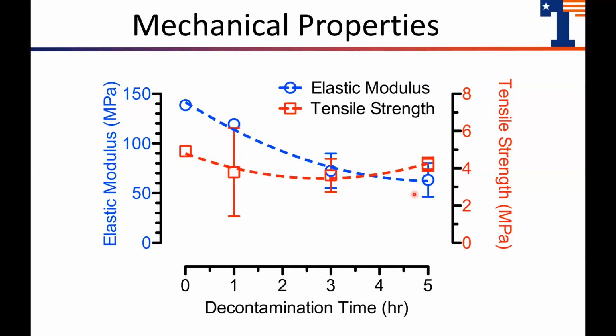Since the elastic modulus decreases, it suggests there's an increase in the plasticizing effect. Then you also have a decrease in the tensile strength. The control was about 4.9 plus or minus 2 megapascals, then it drops to 3.8 plus or minus 2.4 for the 1 hour. For the 3 hour, it is 3.6 plus or minus 0.9 megapascals, and for the 5 hour, it increases ever so slightly to 4.2 plus or minus 0.4 megapascals. Since the control has the highest tensile strength, this suggests that the semi-crystalline molecular structure is being plasticized throughout the decontamination process.